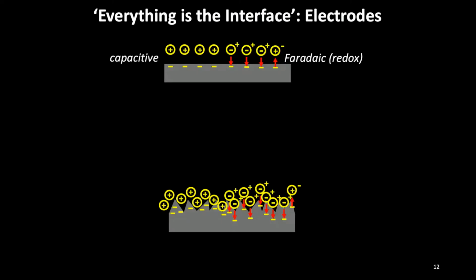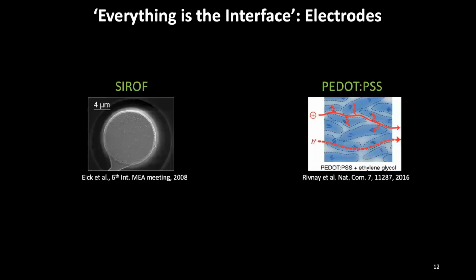There is also the second mechanism, which is Faradaic interaction, where you have redox reactions happening at the interface. And when you roughen an electrode surface, you create dipoles at sharp contacts, at sharp points, and that lowers the work function, making that interaction or redox reaction have a lower energy barrier to happen. So it's not only the surface area, the electrochemistry becomes even better.